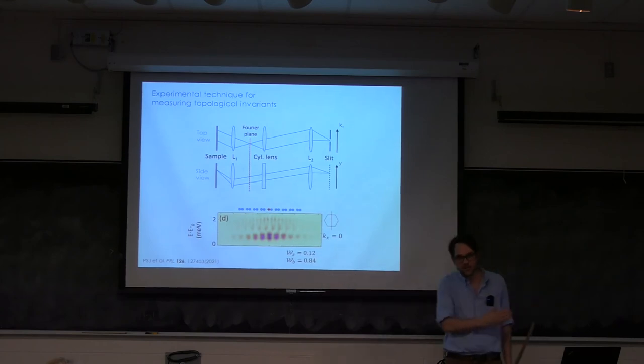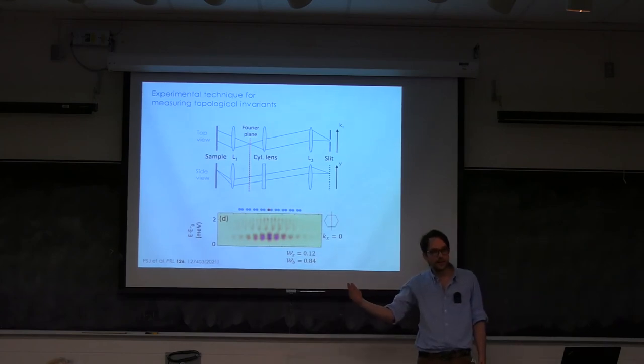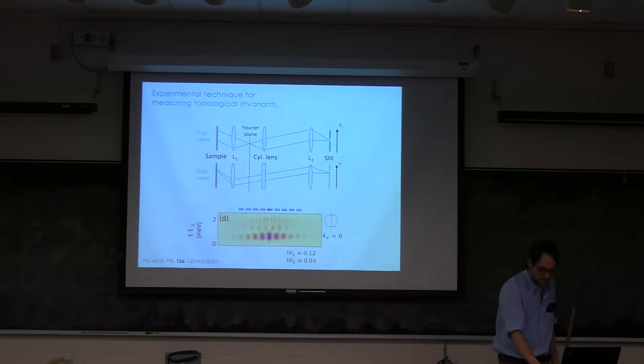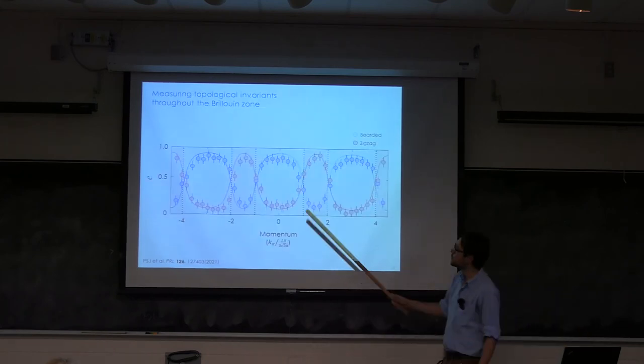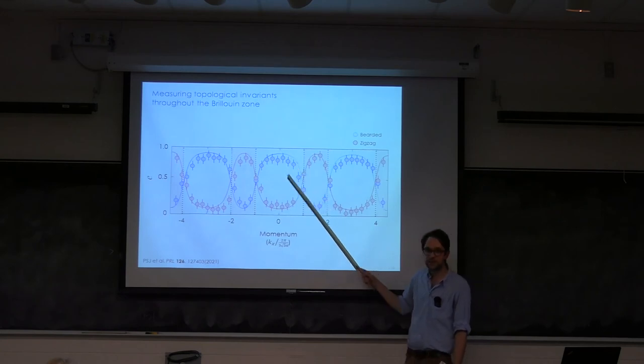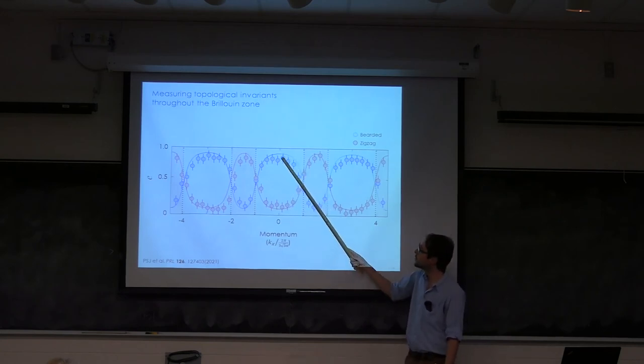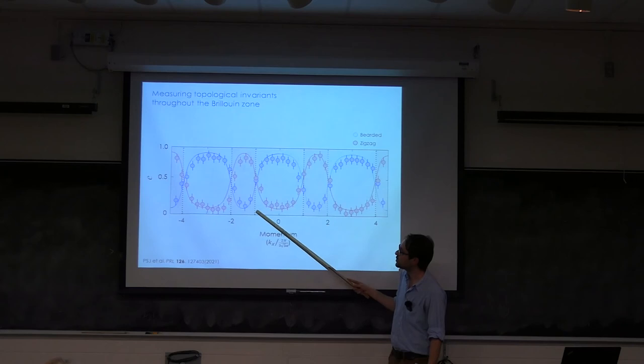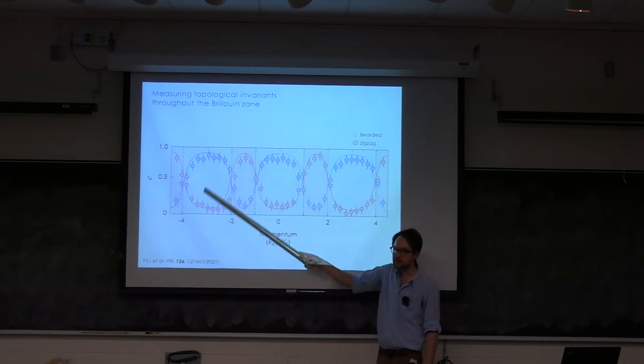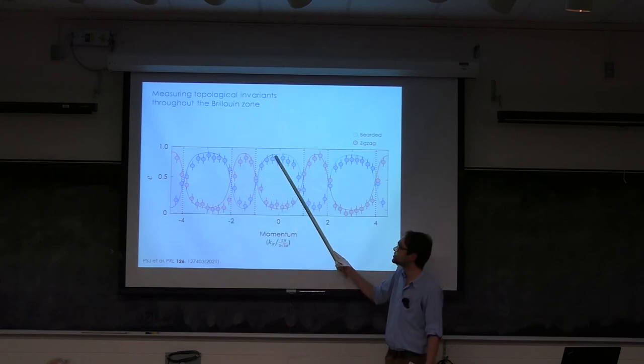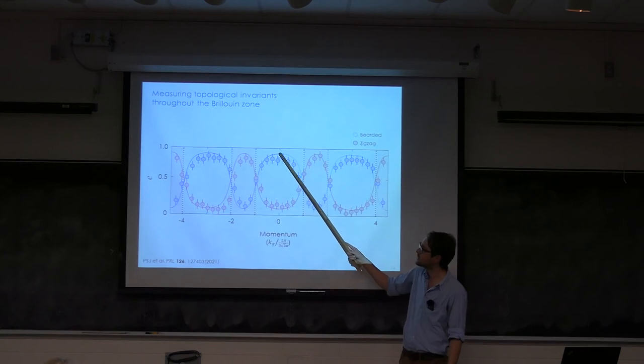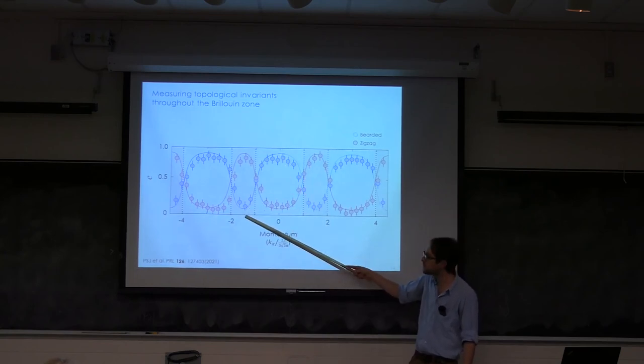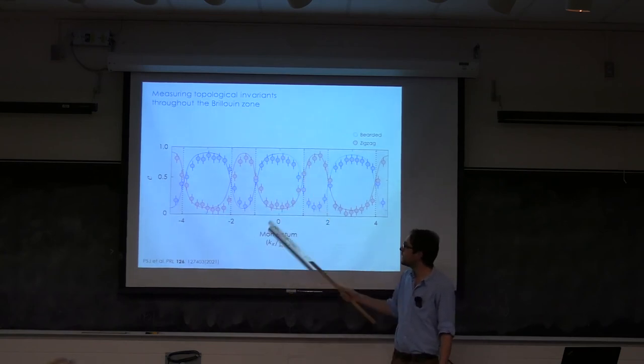And now what we can do is just move our cylindrical lens and span across the Brillouin zone. And so when we do this, we see that depending on how we define the unit cell, our vector of C goes from a high value, and the dotted lines here show the position of the Dirac cones, maximum to minimum to maximum to minimum. And in fact, it never goes to 0 or 1. So there are two things here that worried us at the beginning: it doesn't go exactly to zero, neither to one, and it's not sharp.